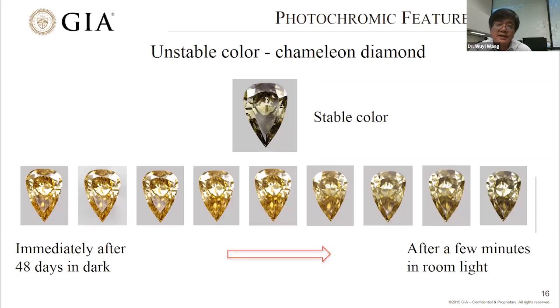And for the same chameleon diamond, we put the diamond in the dark, and we were very lucky. We were able to put this diamond in the dark for 48 days. After 48 days, the diamond turned to a yellow color, a very similar orange color to that after heating, and then when exposed to room light, it gradually restored to its stable yellowish green color. So anyway, what I try to show here is that color is a very important feature of a diamond, and there is quite a lot we still don't know.